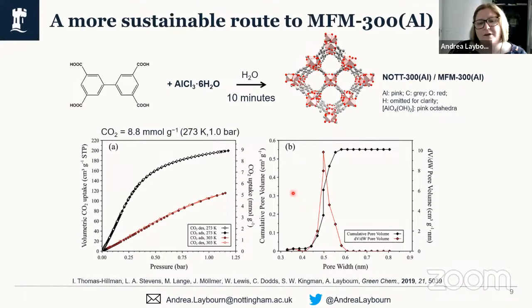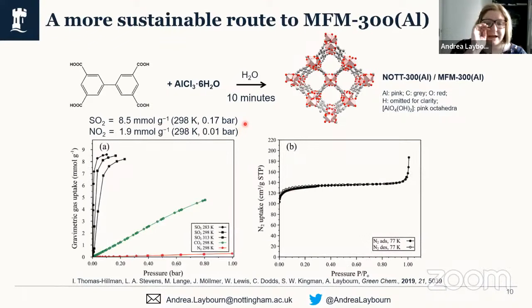But this material is also very well studied for sulfur dioxide and nitrogen dioxide uptake as well. So we investigated the uptake of this with our collaborators based over in Leipzig, and we found that the sulfur dioxide uptake is 8.5 millimoles per gram at 298 Kelvin and roughly around 0.2 bar, and the nitrogen dioxide uptake is 1.9 millimoles per gram at the same temperature and at 0.01 bar. And these results were quite astonishing to us because for the sulfur dioxide, it's 70% greater uptake in the capacity for the microwave synthesized material. And for nitrogen dioxide, it's 90% greater uptake for this material.